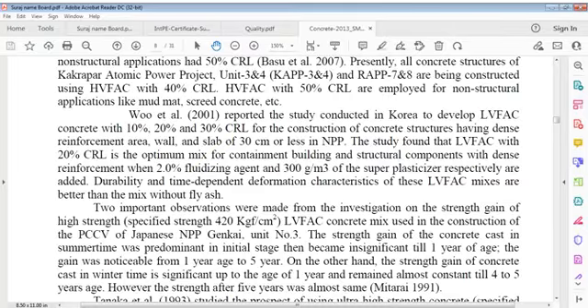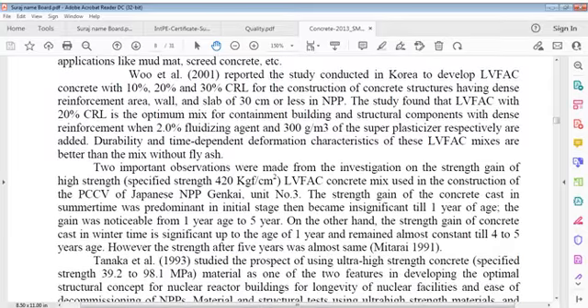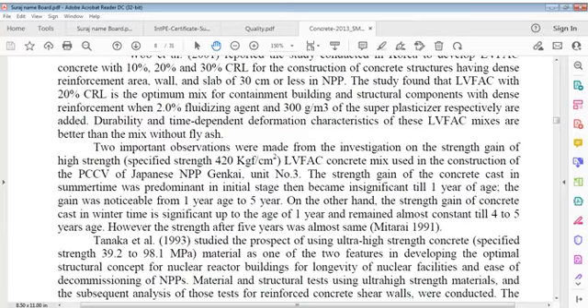Durability and time. Study found that LVFAC with 20% CRL is optimum mix for containment, building and structural components with dense reinforcement when 2% fluidizing agent and 300 gram per cubic meter of superplasticizer respectively are added. Durability and time dependent deformation characteristics of these LVFAC mixes are better than mix without fly ash.